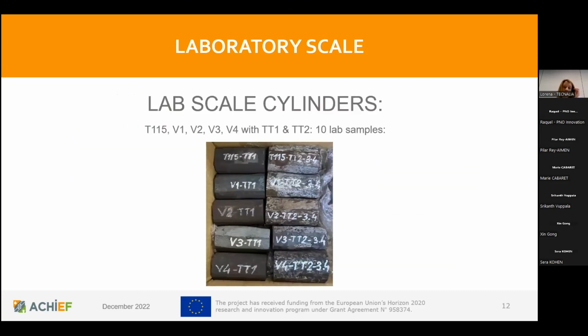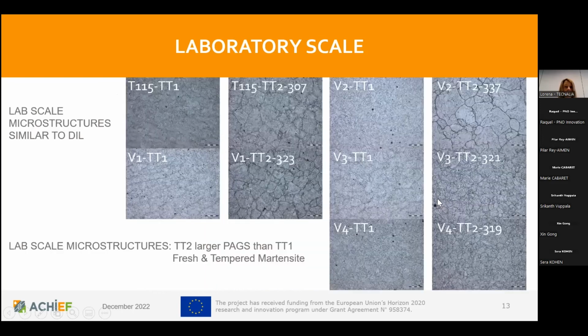Okay, so let's see the characterization of the lab scale samples after lab scale processing. Remember that we have a total amount of 10 lab scale cylinders because we have 5 steels with 2 thermal treatments. At lab scale, the microstructures obtained are more or less similar to those observed at the dilatometry level. In the lab scale, the thermal treatment 2 gives rise to larger prior austenite grain size in comparison to the standard thermal treatment. And we can also obtain fresh and tempered martensites in the steel samples.